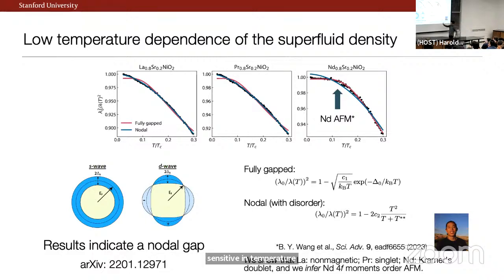But the funny situation is that if I have this kind of gap, the so-called nodal gap structure, where I have parts of the Fermi surface that have vanishingly small gap, that tells me that even with a tiny bit of temperature, I have thermal excitations that I can expect in the system, right? And so if you look in the low temperature limit of these two different cases, one can actually at least make an experimental statement about whether I have a node or not. And the bottom line is that we definitely seem to see a nodal gap structure.